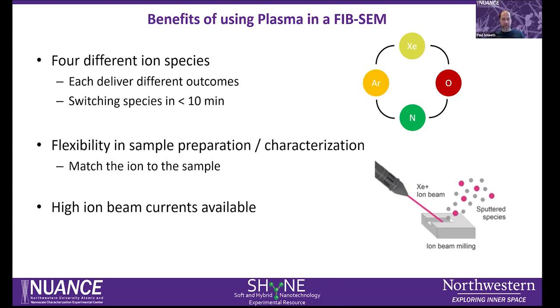In the Hydra, we can switch between species in less than 10 minutes. For example, you could do a coarse cut with xenon and then polish with argon in a relatively straightforward fashion. This gives you flexibility in sample preparation and characterization, to match the ion to the chemistry of your sample.